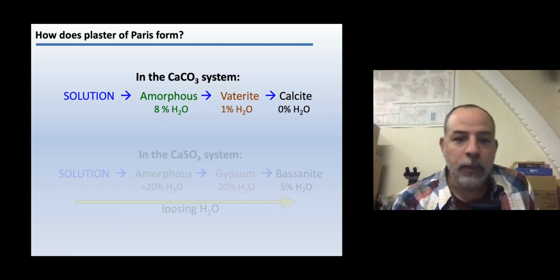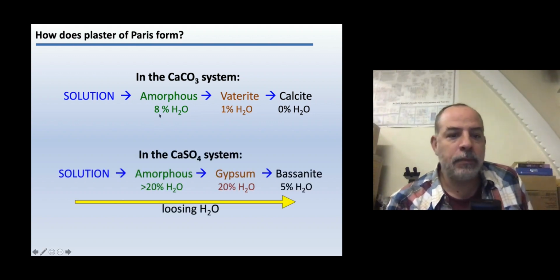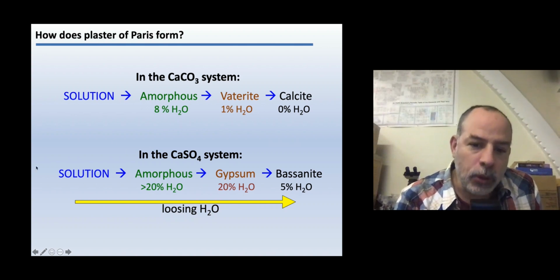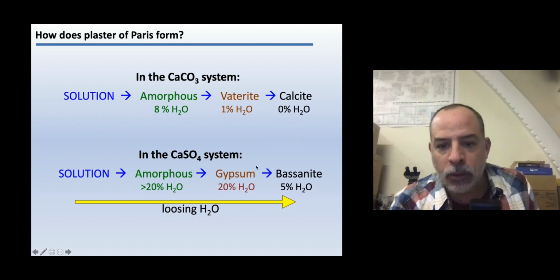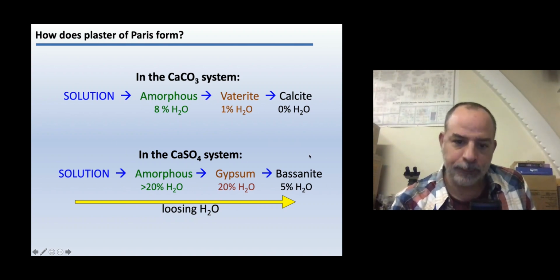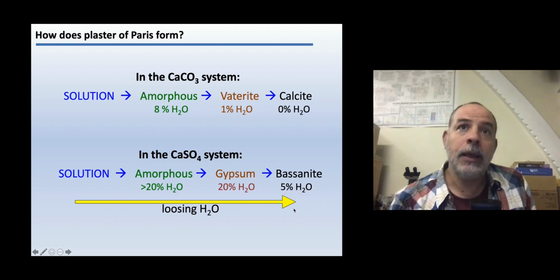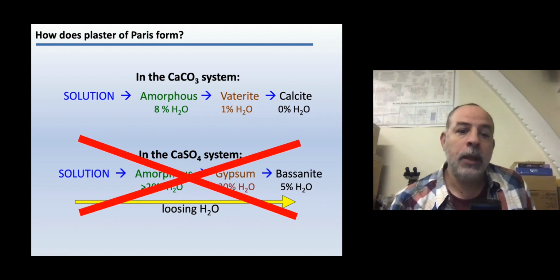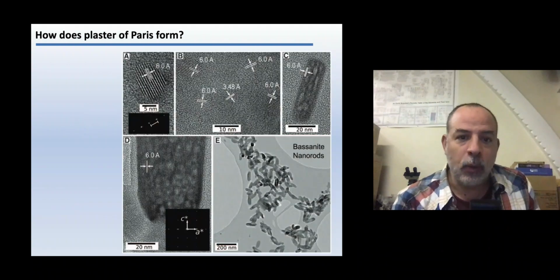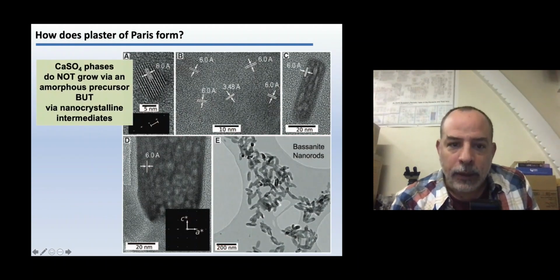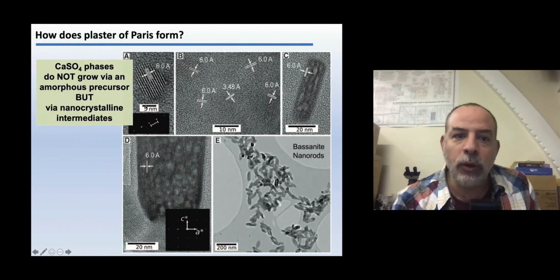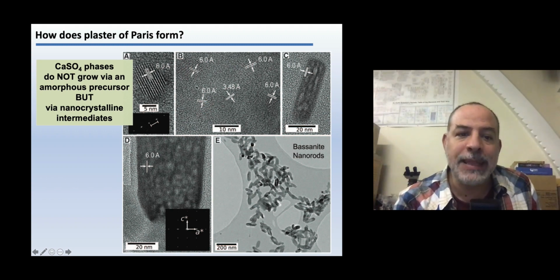So we thought, okay, in the calcium sulfate system, perhaps we will go from solution to an amorphous phase to gypsum and then bassanite by losing water. And we were completely wrong. Okay, it happens something completely different. What happens is that these calcium sulfate phases don't grow via an amorphous precursor. They form crystals from the very early stages of reaction.